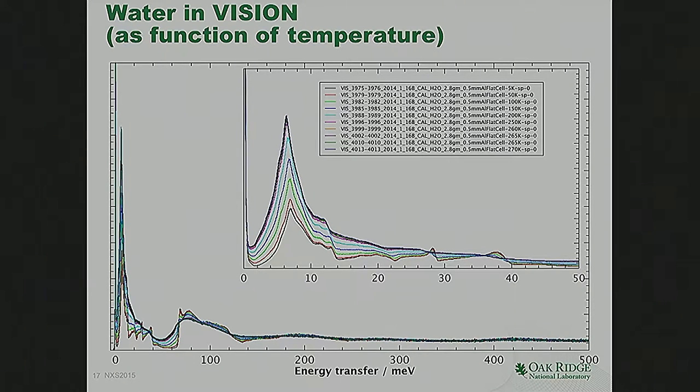I don't know how many of you have done the experiment or what instrument you're using, but in here, at 1 millielectron volt, I have 1,000 points. And here at 10 millielectron volts, in that space when I contain it, I have 1 millielectron volt width, I can put 100 points. And you can see the sort of resolution that you have in there. So this is a phenomenally high counting instrument, and that allows you to look now as a function of temperature, something that we never thought was going to be possible.